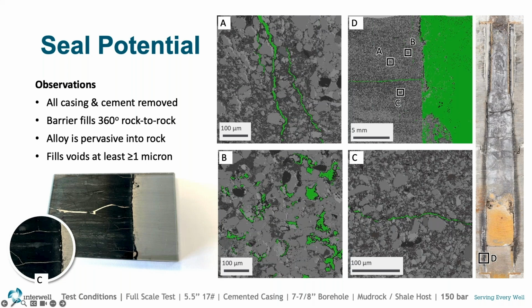So each of these 3 slides, A, B, and C, are showing those various areas and identify that our product can permeate or flow into very, very tiny cracks down to the size of 1 micron or 1,000th of a millimeter. Relating to the previous slide, explaining the difference about bismuth melting and production, the viscosity of liquid bismuth will decrease as temperatures increase, which does allow it to in fact permeate or flow into these very tight small spaces and provide 360-degree rock-to-rock coverage of that surrounding caprock.